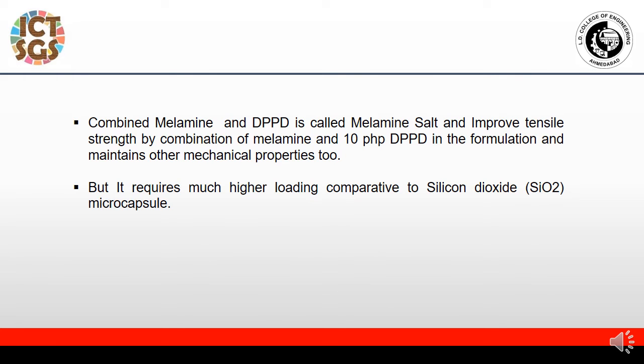Therefore, the combination of melamine and DPPD is used. It improves the tensile strength by the combination of melamine and 10 PHP DPPD in the formulation and maintains the other mechanical properties as well, but it requires much higher loading compared to the silicon dioxide microcapsules.